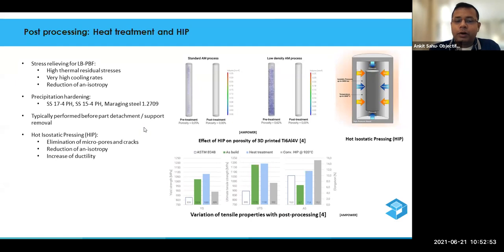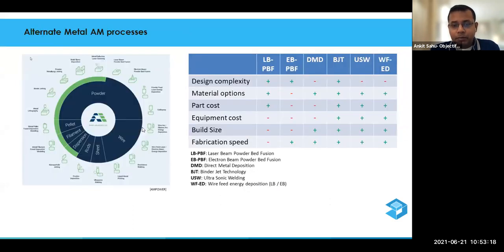Then, for support removal and part detachment, we do it as a stress relieving exercise. Then hot isostatic pressing is mostly done to eliminate the micropores and the cracks. Reduction in the anisotropy can also be achieved through hot isostatic pressing, and it can also increase the ductility of the material itself.